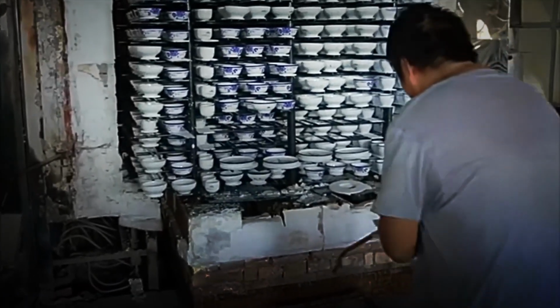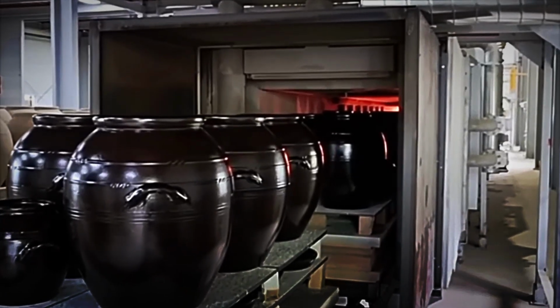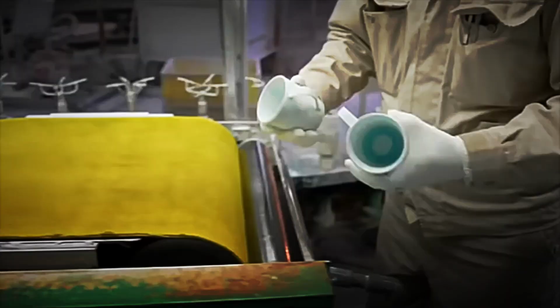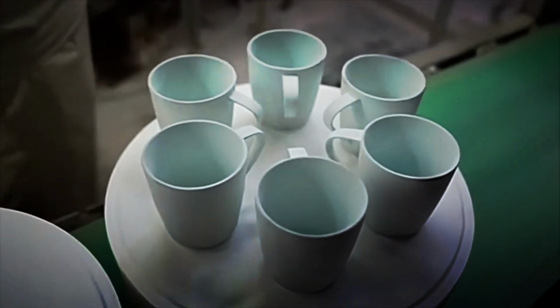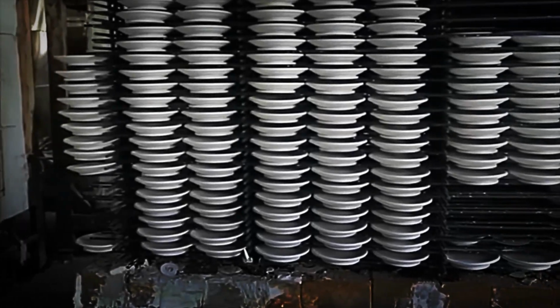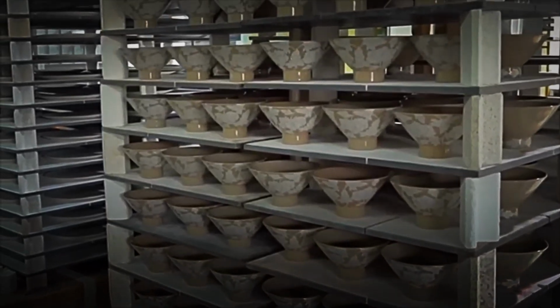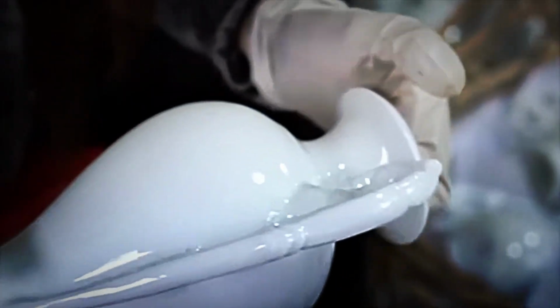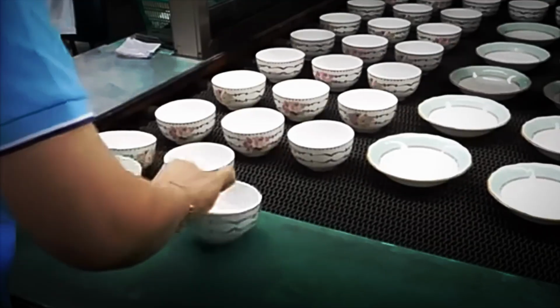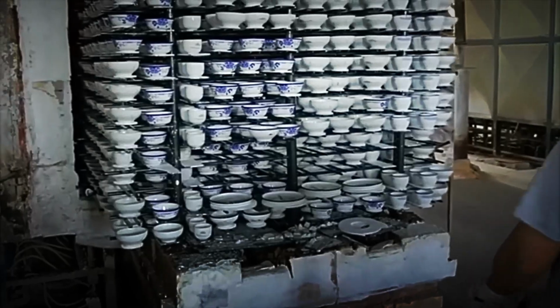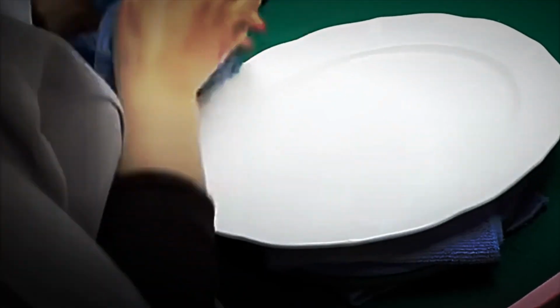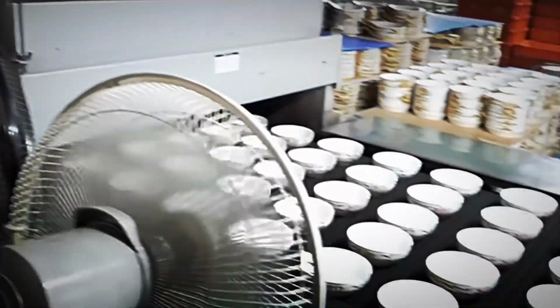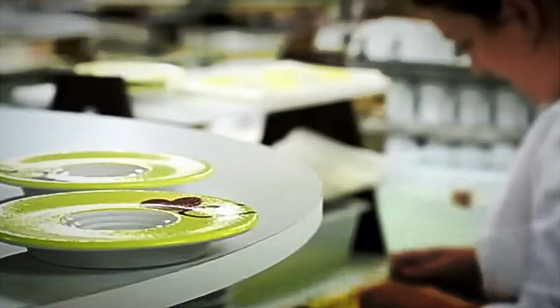Gas burners or electric resistances distributed along the kiln maintain a rigorously programmed thermal curve. Forced air systems, infrared sensors, and automatic controllers monitor each phase to prevent cold spots or overheating. When the glaze reaches its vitrification point, the surface transforms. It becomes shiny, smooth, and extremely resistant to wear. Once the products gradually cool down, they are moved to the quality control area.